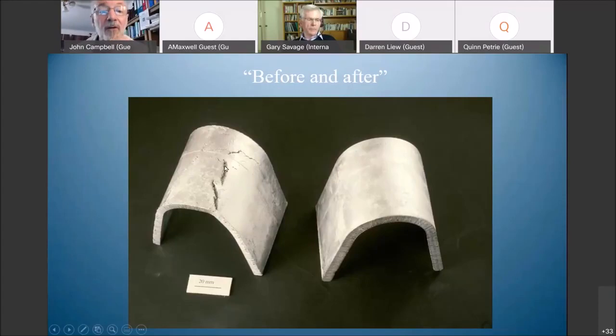And you see these huge cracks. These are centimeters long. There's one here, there's another one at the back. They are massive cracks which can now form. And when you think this is pure aluminium, and we should have been able to bend this piece of casting and tie a knot in it without any defect appearing. And here we've got cracks in something as ductile as aluminium. There's something deeply, deeply wrong somewhere. So these bifilm cracks explain